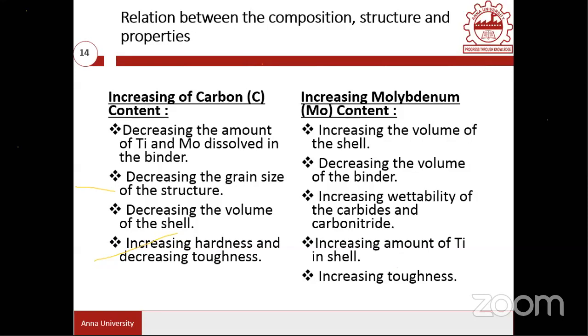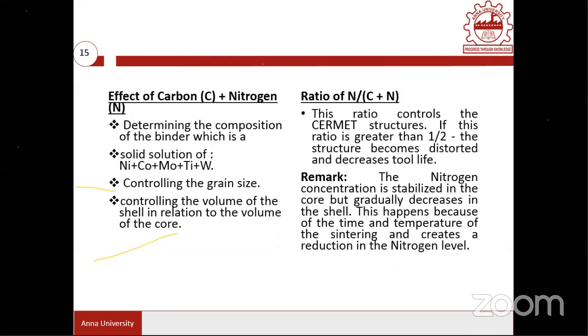Then the molybdenum addition is going to assist the sinterability. That's probably because it is going to improve the wettability. That means the toughness aspect is going to increase. Then if you look at the carbon and nitrogen content, it is going to make a solid solution with the other metallic elements. So the nitrogen and carbon will form a solid solution with nickel, cobalt, molybdenum, titanium, and tungsten, and it is going to control the grain size.